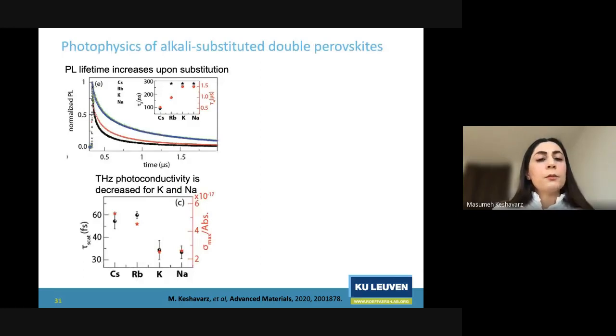Then we performed transient photoluminescence measurements in different time windows as well as detection windows. The time windows range from picosecond to microsecond, and we also measured in different wavelength windows for the detection path. So we measured from, let's say, 500 to 800 nanometer, one curve at each wavelength. And through that, one can access the decay associated spectra for each lifetime.